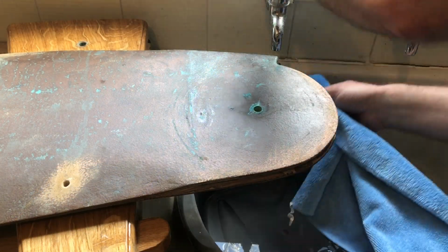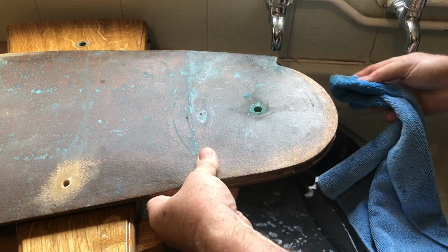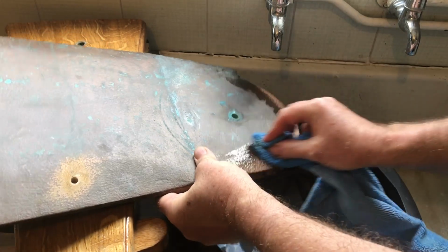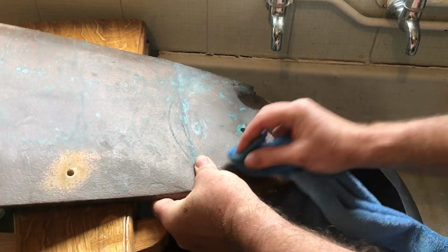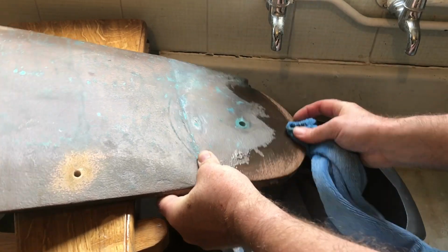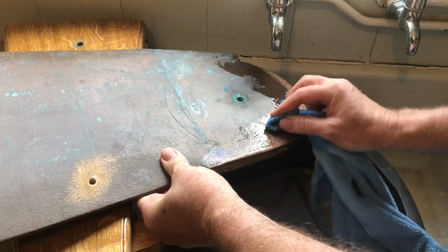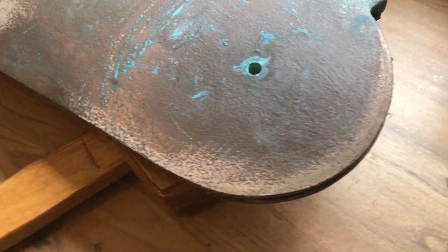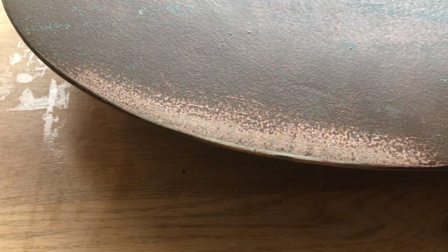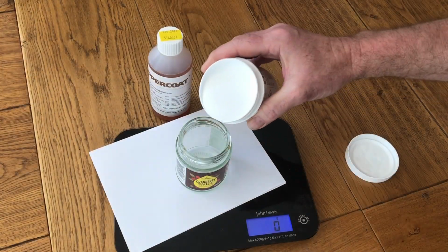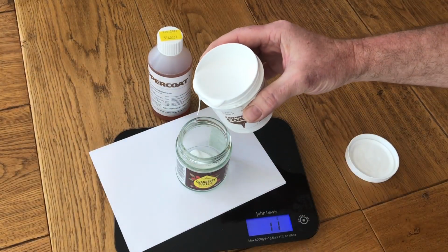The sanded areas should then be washed with fresh water. Best not to let any Coppercoat go down the workshop plug hole, so I caught the waste in a bowl which I'll filter later on. Once the blade was completely dry, it was time to mix the Coppercoat. The resin and hardener mix ratio should be 1:1 by weight.